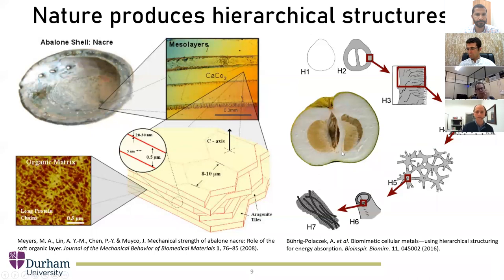And also when you look at this peel, it seems to be made of multiple levels of hierarchy. So it's a porous material, a little bit like our steel foam, but it is made of struts. So it's like a truss or frame made of thin tubes. Each tube is kind of small, but it's a hollow circular tube. And if you zoom in and you look at the walls of the tube, it's basically a fibrous composite.